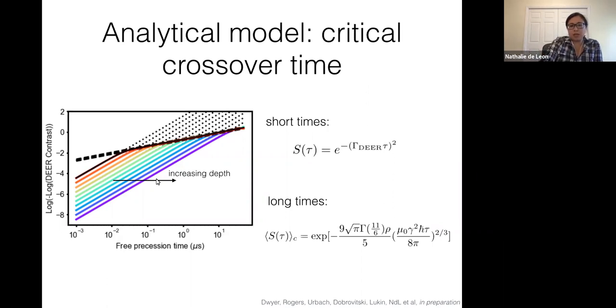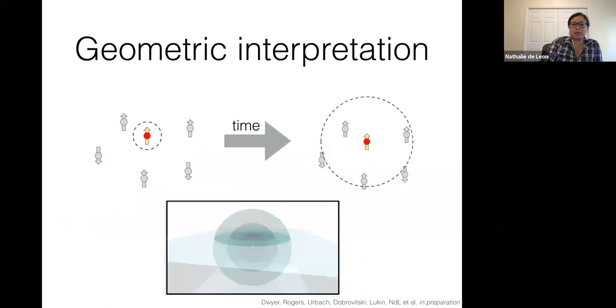Okay, so putting the numerics and the analytical model together, there's a nice physically intuitive geometric interpretation of all of this, which is that the NV center, after some given time, really just senses some particular volume, right? And this volume grows with time. Because it's spatially separated from your 2D bath, there's some time delay before this sphere intersects the surface, at which point you start integrating over the area of spins at the surface. So this kink in time is directly related to the depth of the NV center.